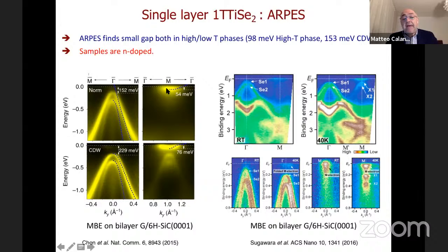And there is a band at M that is partially occupied, as you can see, and this is a D band of titanium. However, the point is that the system is a perfectly compensated system. So it means that if you have holes in the titanium bands here, so it means that you have hole pockets, then you must have electron pockets. But if this band is totally occupied, this band should be totally empty. However, the system does not exist in purely stoichiometric form. The system is always a bit n-doped. And this is the reason angle-resolved photoemission can see this band at the M point.